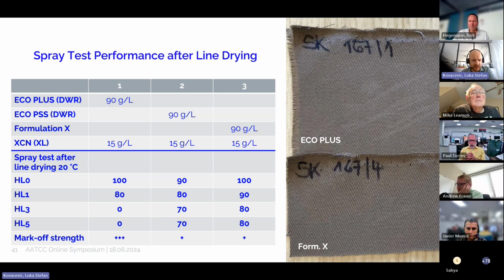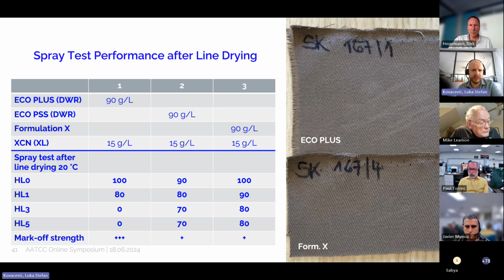So you can see that after a number of washes, the Eco Plus loses performance after line drying quite quickly. Mark-off is relatively strong. Eco PSS starts off with a lower initial spray, but can keep a moderate water repellency after line drying over a higher number of washes. And here we have something that I call Formulation X. It's not a product yet, but we can improve the initial spray to a level of Eco Plus, and we can also improve the line dry water repellent performance. You can see that even after the 5th wash, you can have a grade of 80 in spray testing. Mark-off is really good. This is something that we are working on right now.